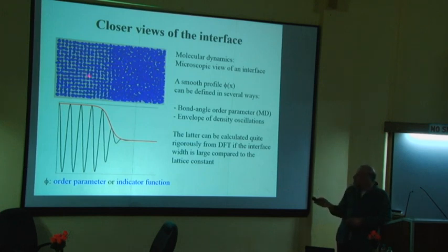So in the solid, the structure is ordered, it's cubic. Since all the atoms are in one row, you can sort of view through it. So here you have an ordered structure. In the liquid, it's difficult to see by eye, but the density is almost the same, but it's a disordered structure. And you see that the order doesn't disappear all of a sudden. There is a sort of intermediary region where it's partially ordered. For example, here you can still see something like a layer, but it's much more diffused than here.